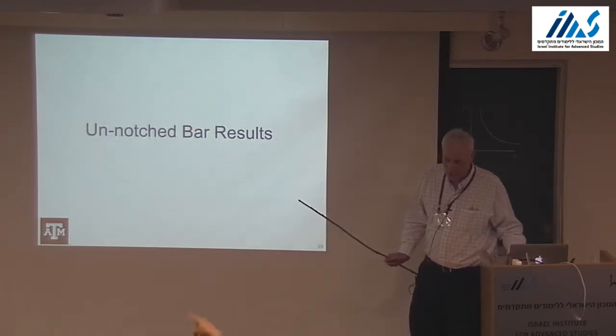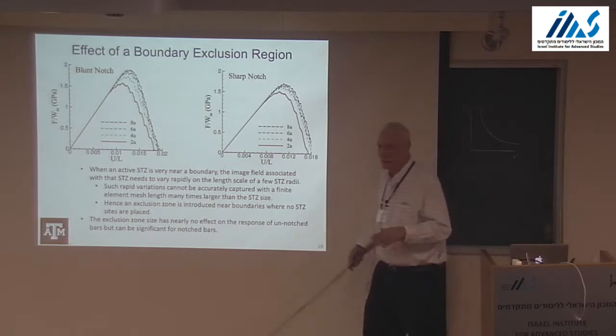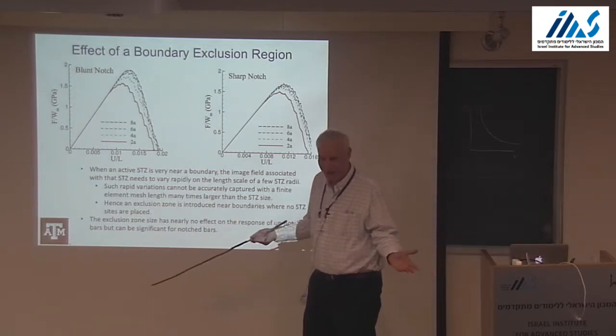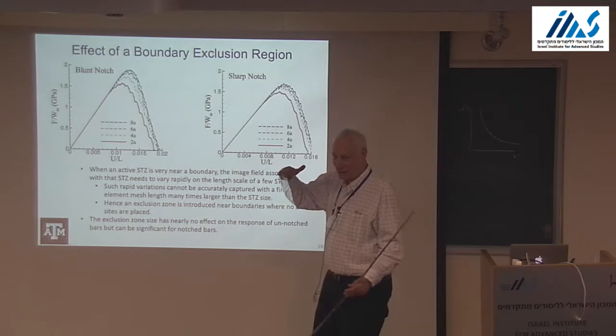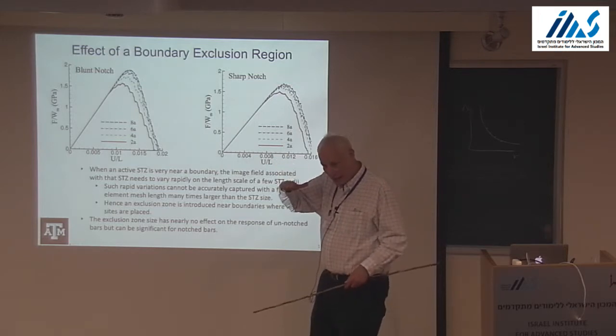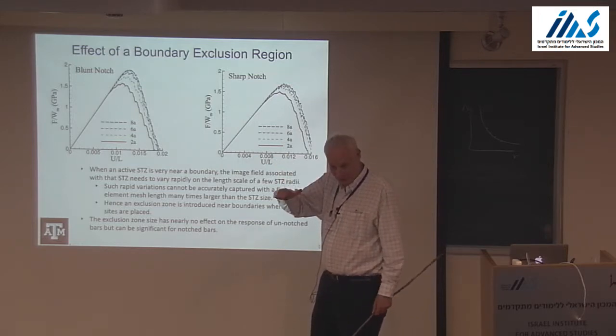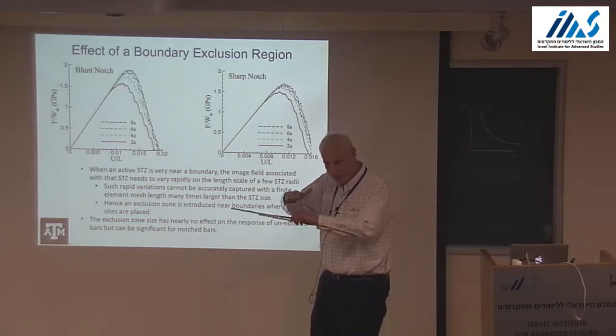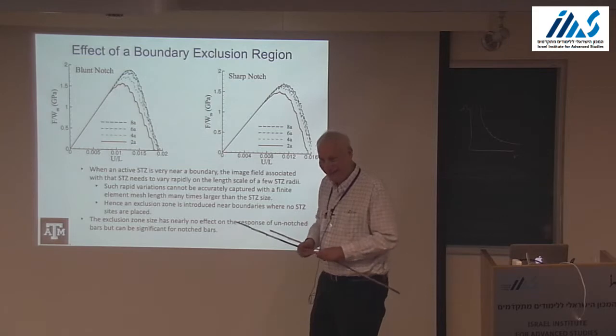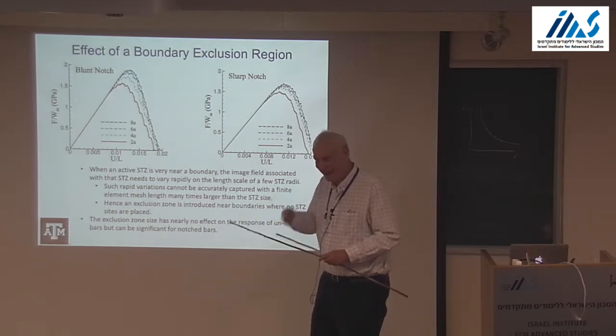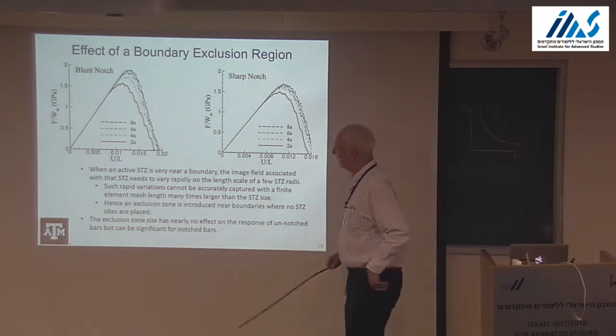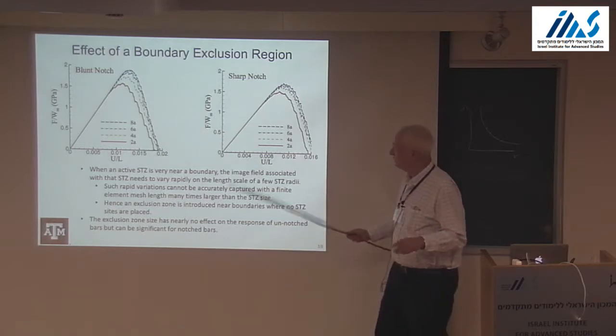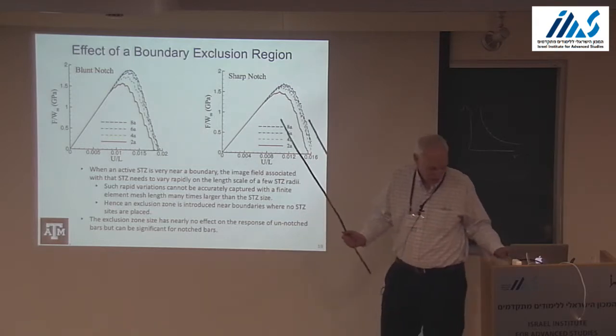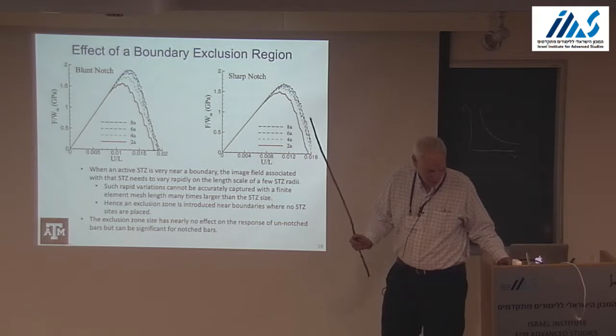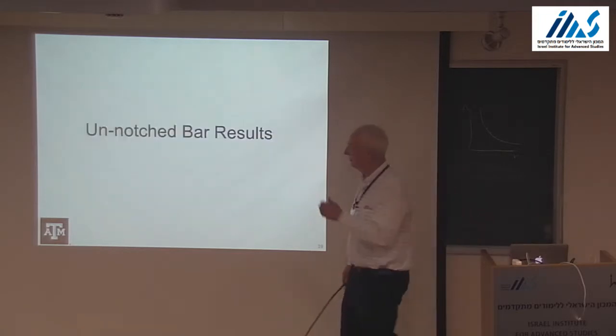So does it always break after the peak? No, because we have no fracture. So why does it go down to zero when you increase the space? When you go to each time, you get softening due to the relaxation of elastic energy. And so the energy just goes down, down. It's the same threshold, so it fires again and again and again. And that depends on the delay time. Sometimes you don't get that going down. If they refire very frequently, you do.